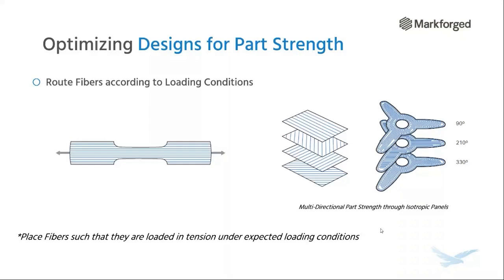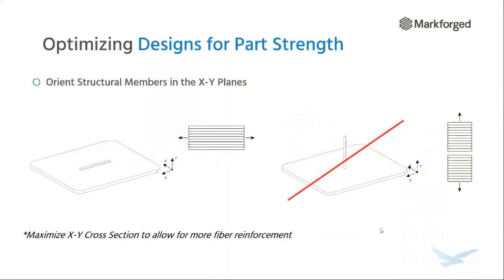The next one I want to tell you about has to deal with print orientation. And this is very similar for other systems that use the fused filament process. And this tip is to orient your structural members in the X and the Y planes. Now this is very important for fiber reinforcement, because the fiber is actually laid out in the X and the Y plane. And so the key here is to maximize the amount of cross section in that plane, in the X and the Y planes, so that you could fit more fiber in.